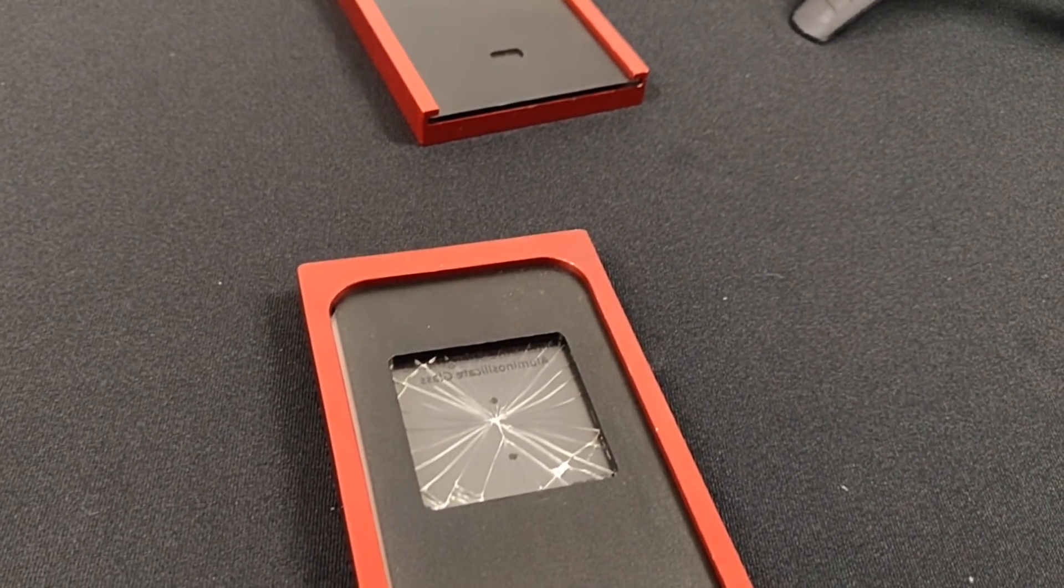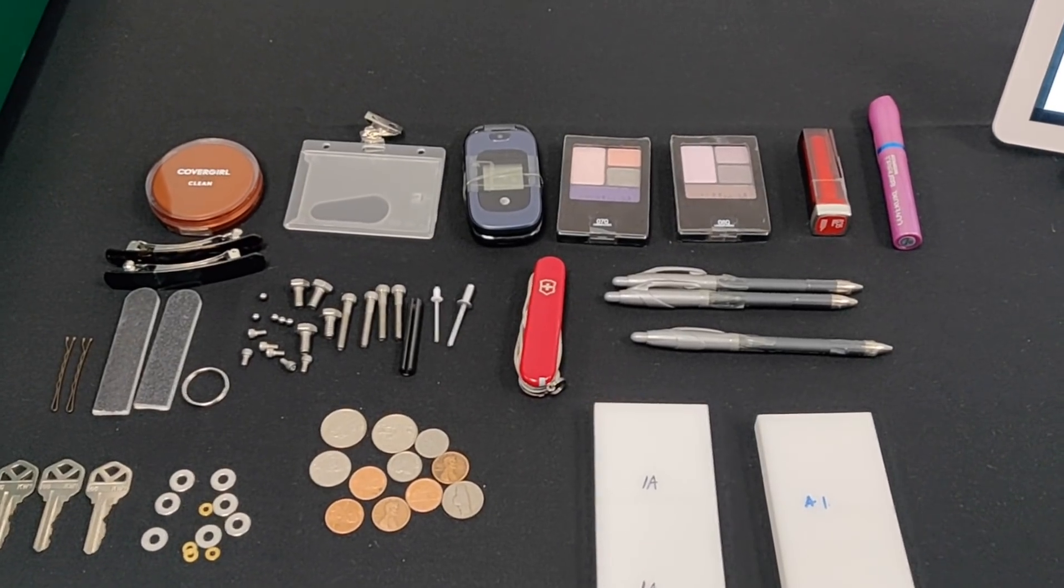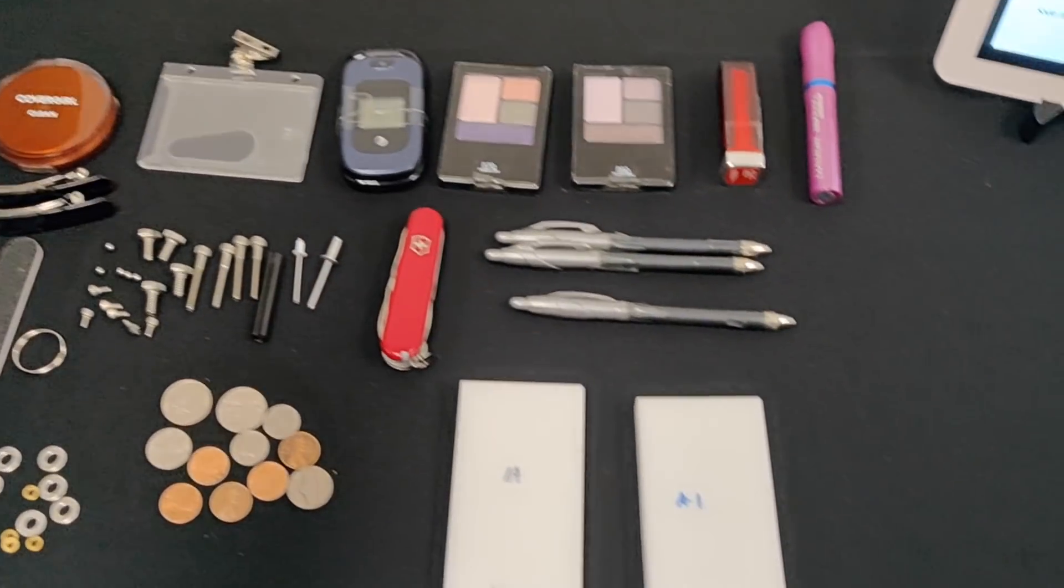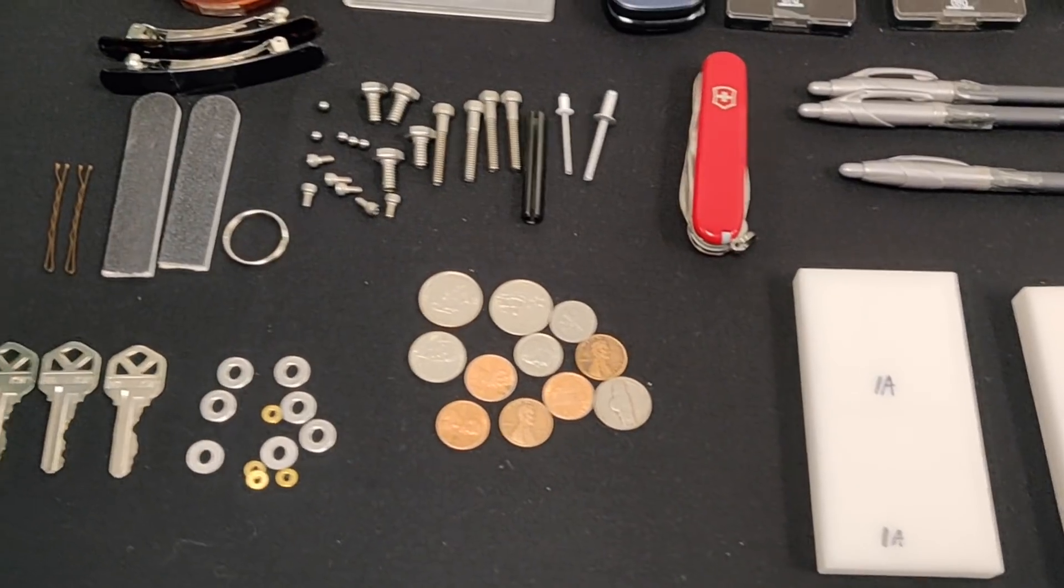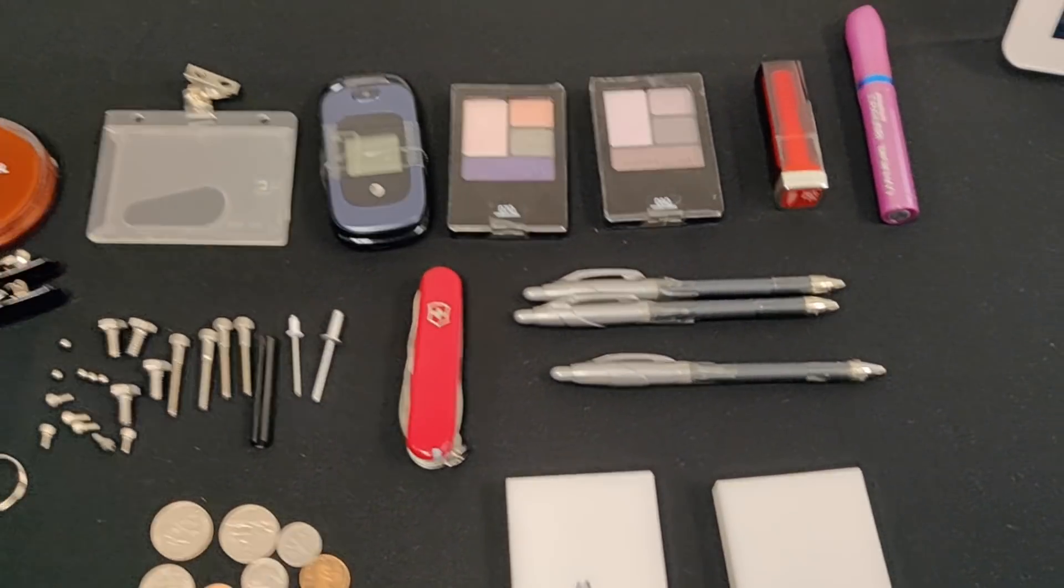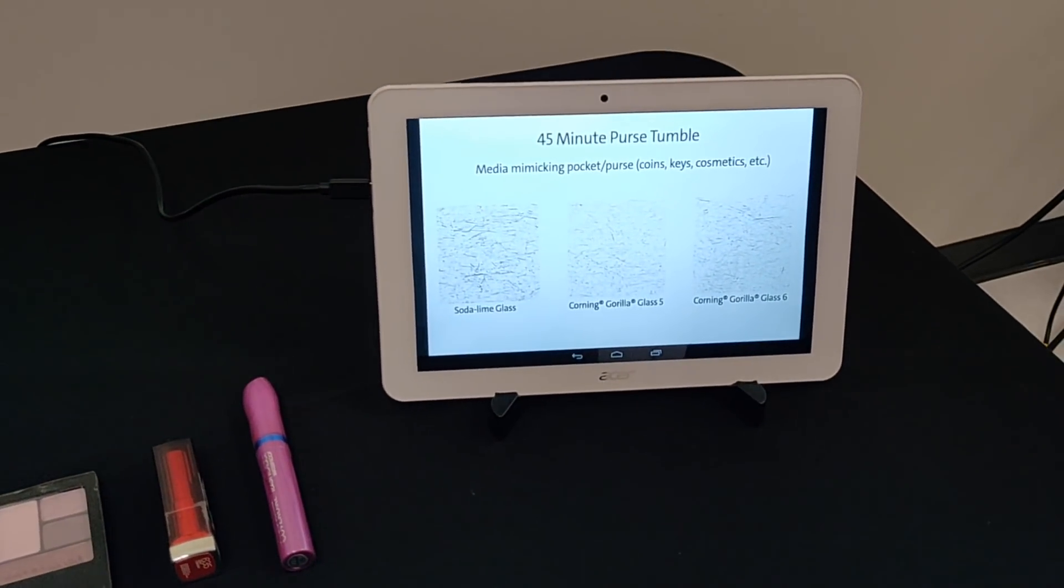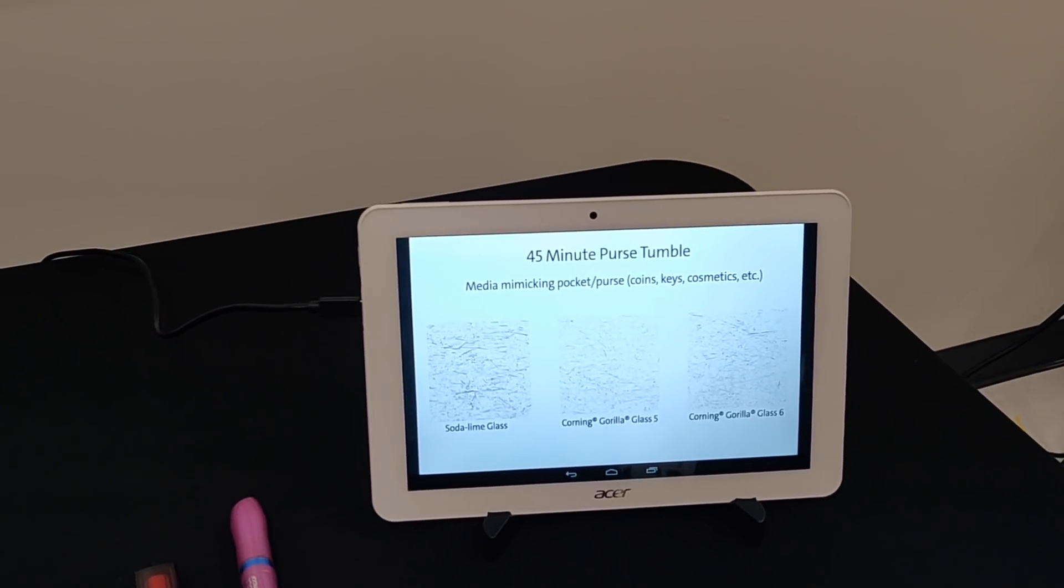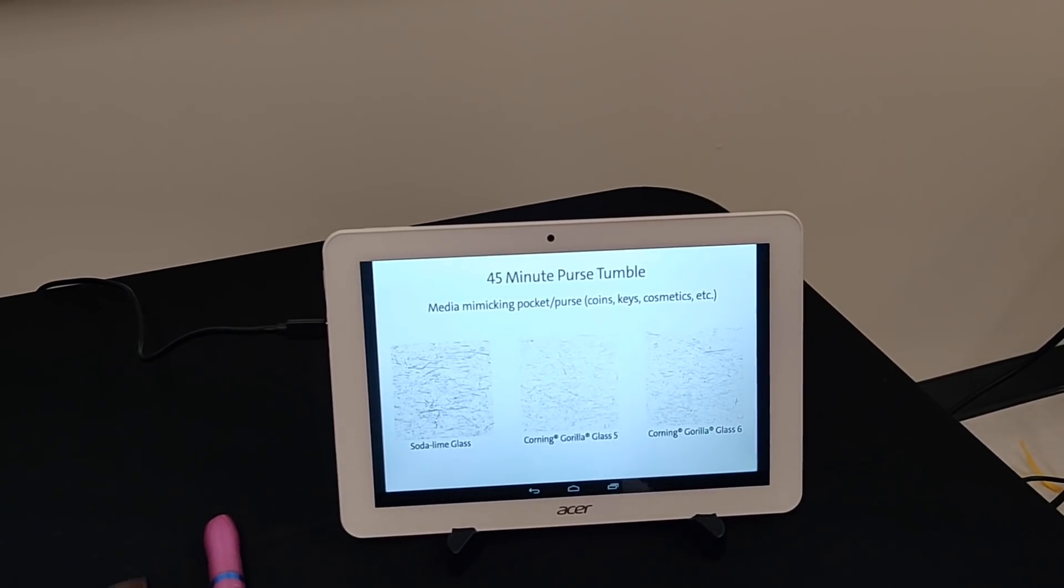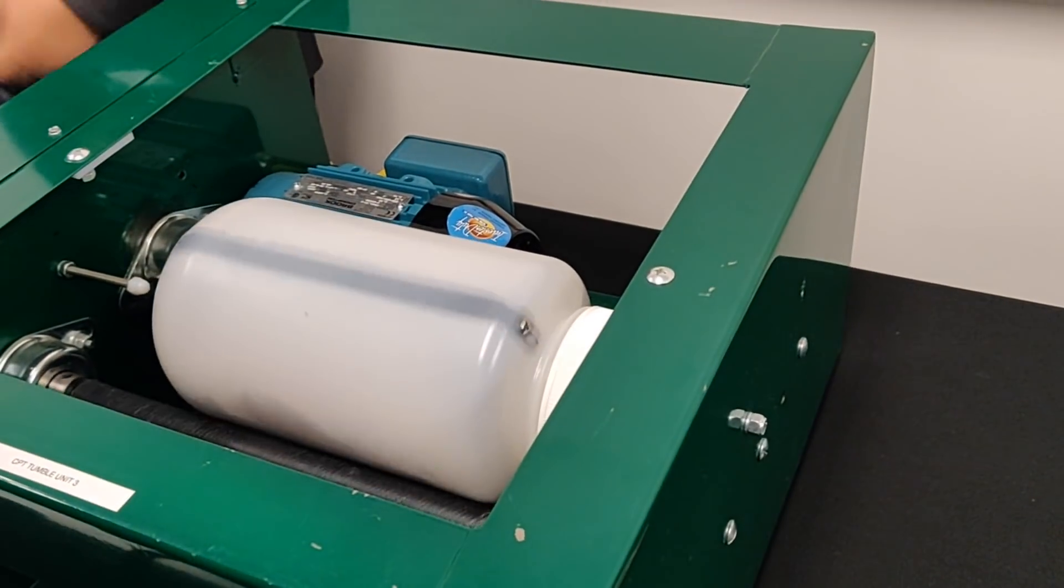The last thing, we just have a couple minutes left, I want to show you is on the table right behind you over here. All of the items that are in this barrel are laid out on the table. The white pucks are typically where we affix pieces of glass. We tape them, we throw them in the barrel, and we tumble them for different periods of time. On the tablet you can see the picture, what you're looking at is the black is damage that's been created from the test. The soda lime has a lot of damage. The Gorilla Glass 5 and 6 have much less damage but are comparable to each other. So I'll turn this on for a minute and let you take some video if you like.